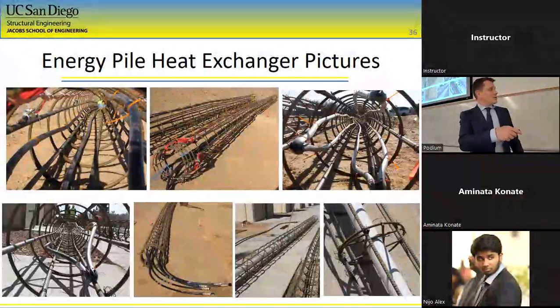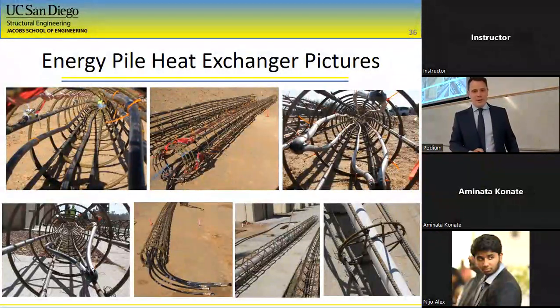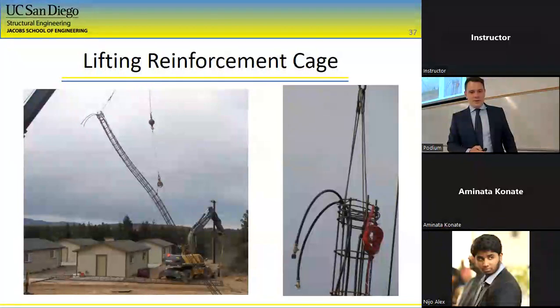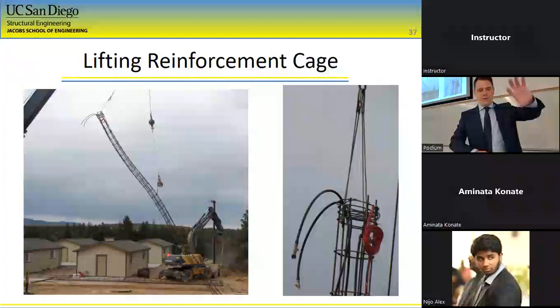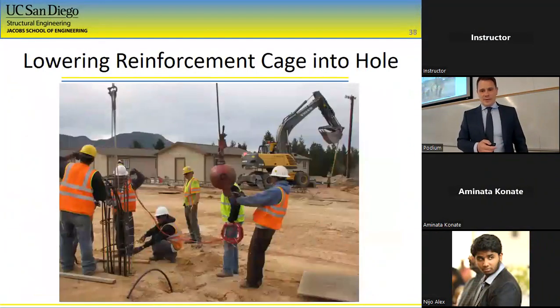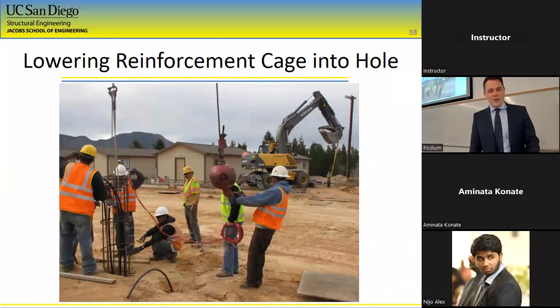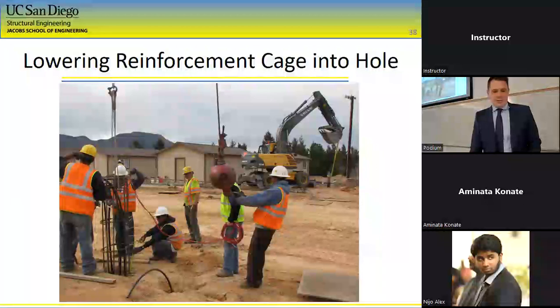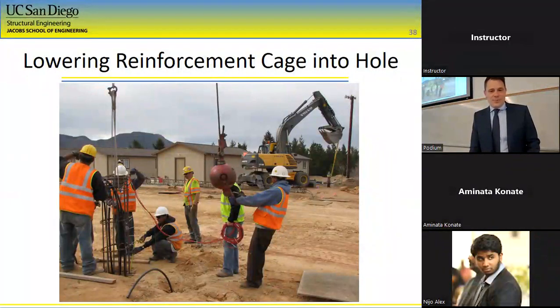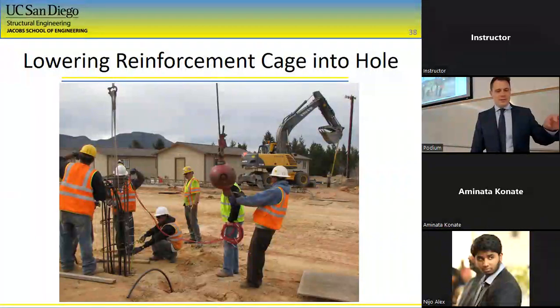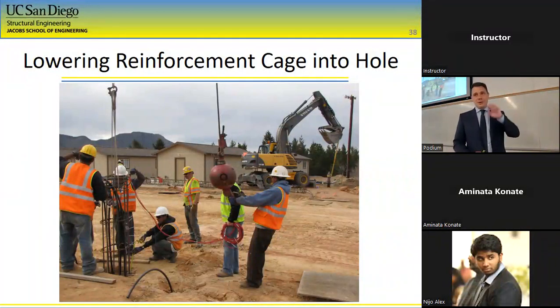We pressurize them all with water before we put them in. And then we lift it up in the air, so it's like a long spaghetti without having significant bending. And then we lowered it into the hole. Because this was sandstone, we used the open hole technique. There are some good things and bad things about the open hole technique. It's very difficult in this technique to clean out the material at the bottom of the toe.